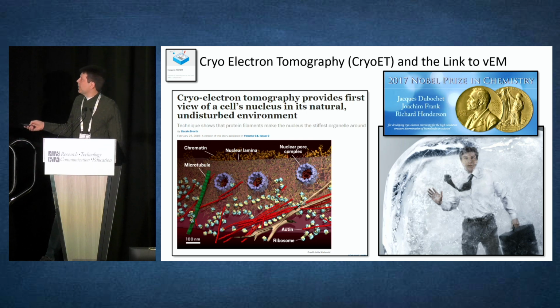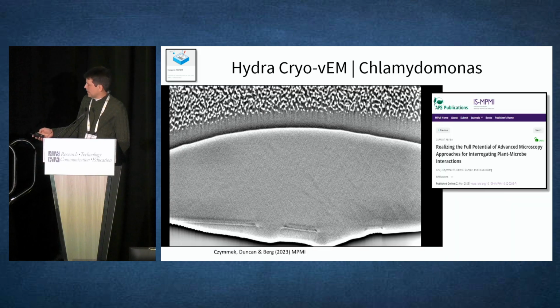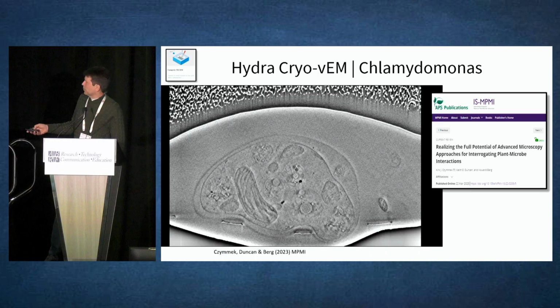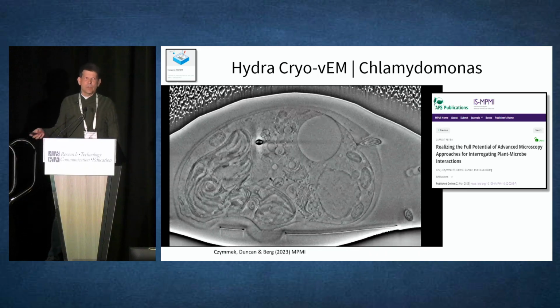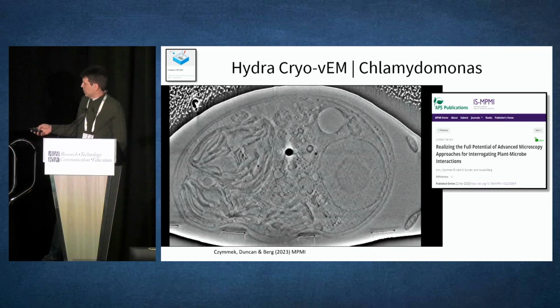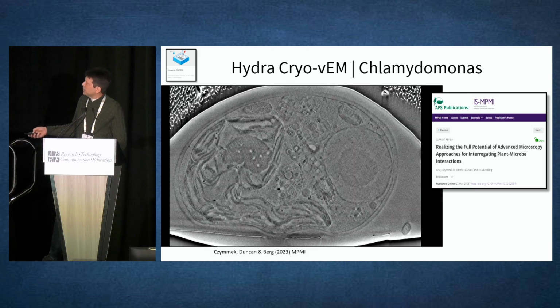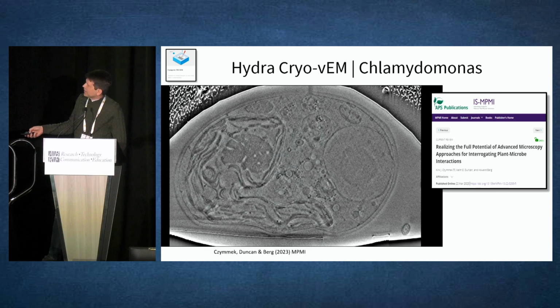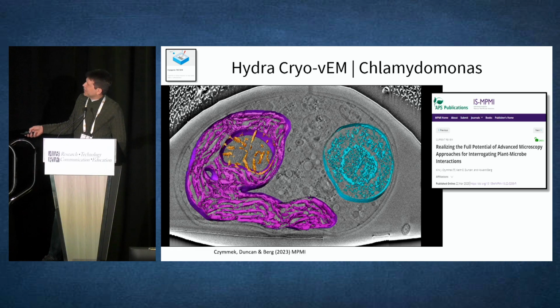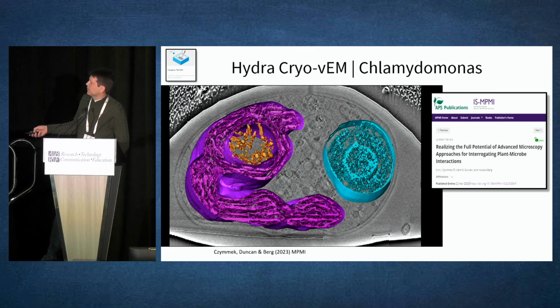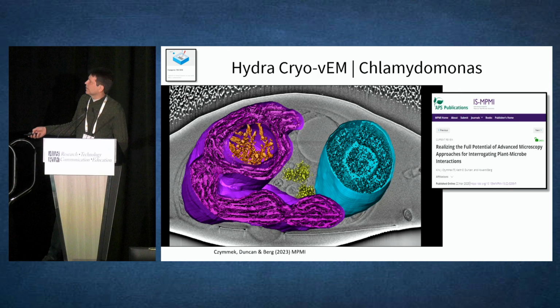And I want to remind you, you can make lamella and so forth on these tools, but you can also get volume data and you can put it both together. And here's an example of an algal sample in which we're imaging unstained, frozen hydrated at liquid nitrogen temperature, and all the structures that you're seeing, the nuclear envelope, the nuclear pores, the stacking of these membranes called grana, they're 10 nanometer spacing on here, so you can resolve very easily down to lower levels.